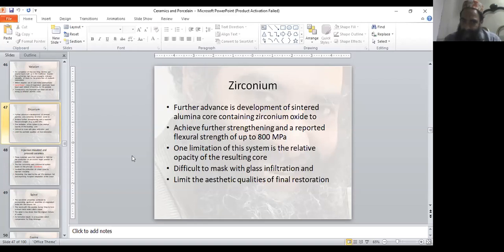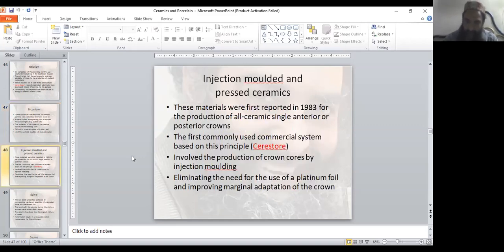Now, further advances and developments are there with zirconium: sintered alumina cores containing zirconium oxide. For what? To achieve further strengthening, and a reported flexural strength of up to 800 megapascal is there. One limitation of this system is the relative opacity of the resulting core, because zirconium is opaque, and this is difficult to mask with glass infiltration and limits the aesthetic quality of the final restoration.